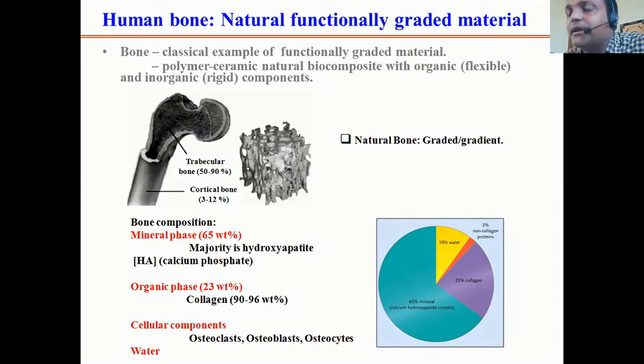Despite the similar composition of ceramic and polymer, or apatite and collagen, the porosity increases. This provides the functional gradation to the bone because inside it is a highly porous structure. You can see at trabecular bone, it is around 50 to 90% porosity. This porosity is required to regulate the metabolic activities of the bone, because we need to supply blood and nutrition for its growth. So this is a different issue.